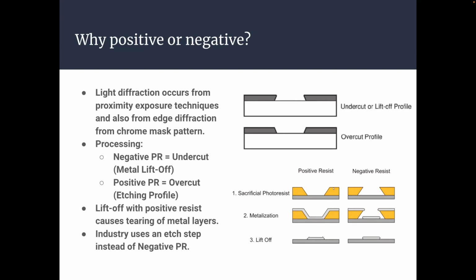For negative photoresist, you can see that with the positive, when we do metallization layers, we have a complete coverage of metal. So it's hard to get into our photoresist and develop that out. Instead we use a negative photoresist, as you still have space to wash away that photoresist itself. And since we would completely metallize our positive photoresist, when we wash away the photoresist, you get some cusping and tearing of the metal, which doesn't happen for the negative photoresist.